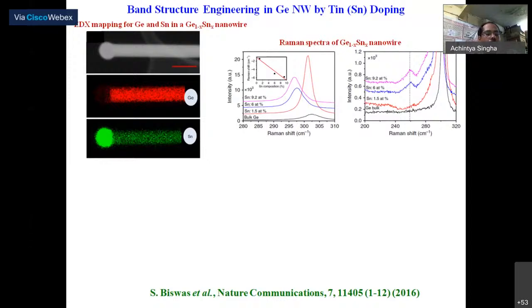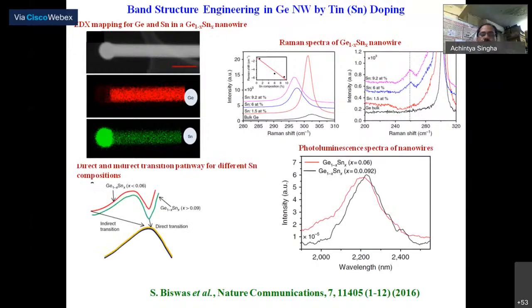The left side is the EDAX mapping of the tin-doped germanium nanowire, and on the right side you can see the Raman spectrum of this tin-doped germanium. We can see how the peak position is changing, and from this change of peak position we can estimate the percentage of tin present in the system, and also get the other vibrational modes present in this nanowire. Finally we did an optical measurement, that is photoluminescence. Go next. Here you can see that this germanium behaves like a direct band gap material, and that paper has been published in Nature Communications.